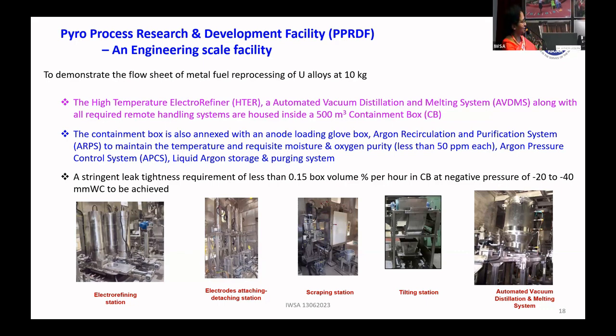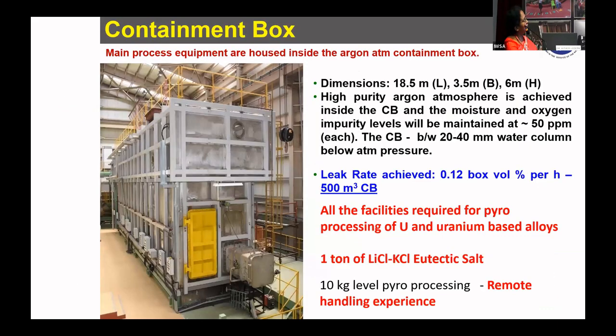So we went for this construction, where all the electro-refining station, electrode attaching and detaching station, scraping facility, tilting of uranium with salt, and automated vacuum distillation facility to distill the salt as well as melt the uranium are housed. And you can see this is the containment box which consists of the entire unit, which is 500 meter cube, and we have prepared 1 ton of lithium chloride, potassium chloride salt, which you can imagine with stringent purity. And this is through 10 kg level of pyroprocessing with remote handling experience.